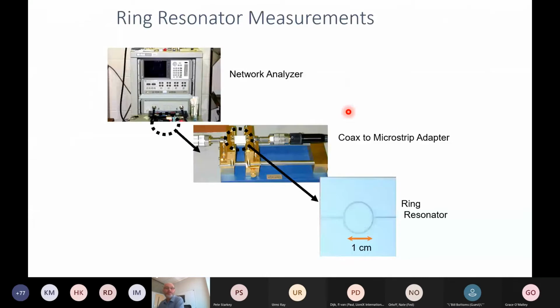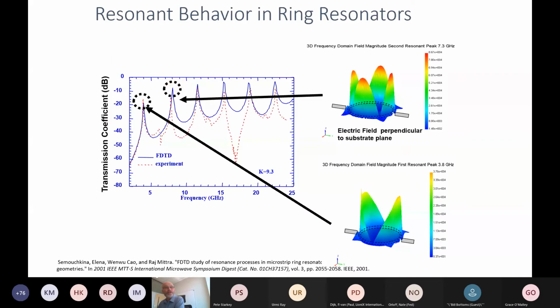The way we did the measurements, basically after we screen printed on these rings, the bottom conductor ground plane is not shown here. We were able to then load that up into our fixture, converting the coax to microstrip, shown here. And of course, then we put this fixture, tied it up to our network analyzer, shown here. And the data we retrieve from that is shown here, just an example where we show the resonant frequencies here.